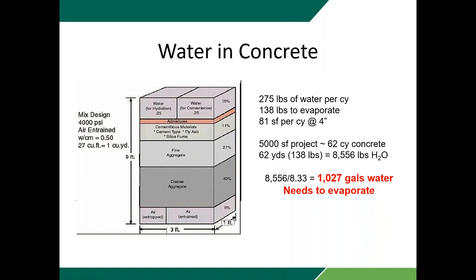So if I look at a given yard of concrete, let's say this is a 4,000 PSI mix, which is typically going to have about 275 pounds of water in it. Of that 275 pounds of water, half, about 138 pounds, is there for convenience, and that needs to leave the concrete, or will leave the concrete if we let it.